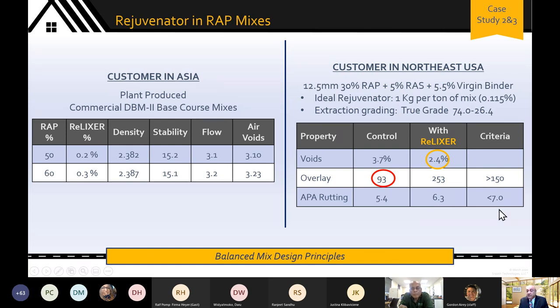The other area that I want to emphasize is this circle. In general, remember I told you earlier, the more high RAP situations you start getting into, and particularly with rejuvenation, you're asking more and more of that RAP binder to behave like virgin binder. So if you do not reduce your virgin binder when you're making high RAP mixes, you will tend to produce a very dense compaction. And this is stuff, by the way, guys, at least in the US, if you had this kind of a void volume, you're not getting paid for that job. So just a cautionary note, when you get into high RAP mixes, you need to consider how much virgin bitumen you're adding. You can't simply do business as usual.